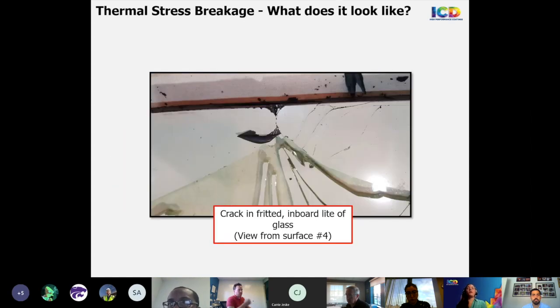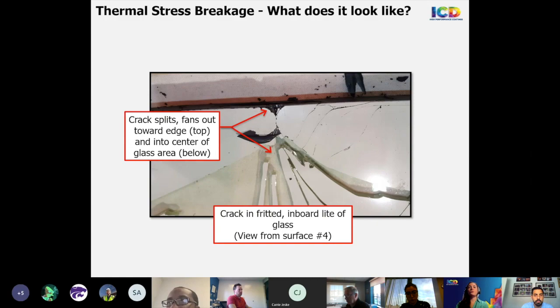So taking that unit out and flipping it around, now we are looking at surface number 4, which is referring to the interior facing surface with an applied ceramic frit. The crack is on top and moves downward toward where it fans out to the center of glass area, and the crack progresses toward the edge of the glass, fanning outward in that direction as well.